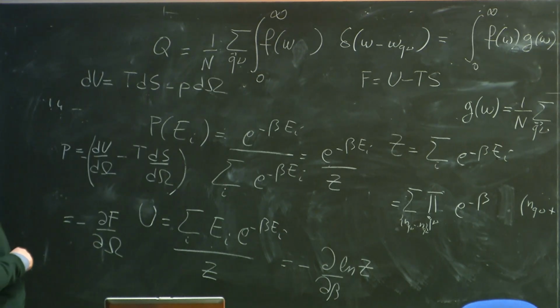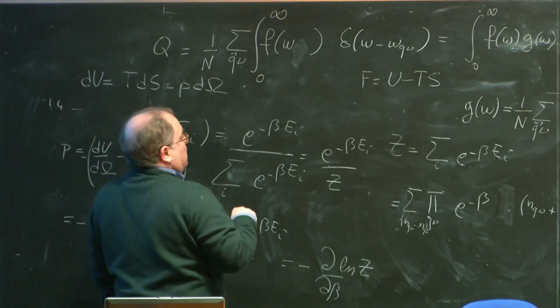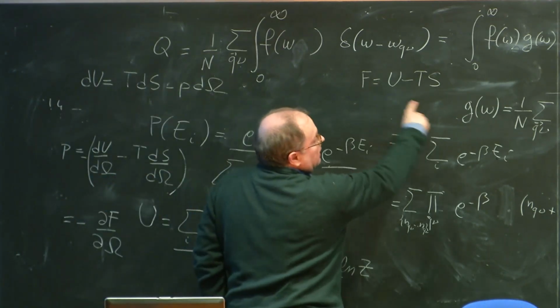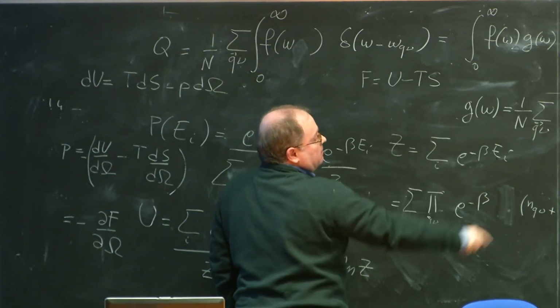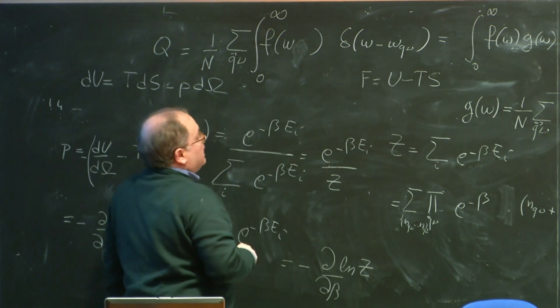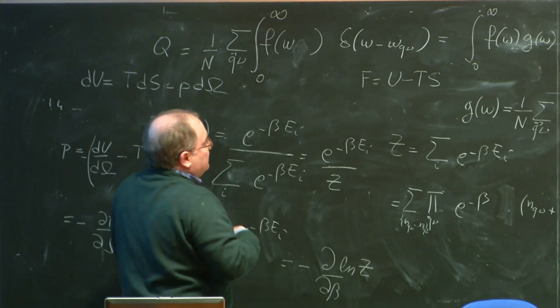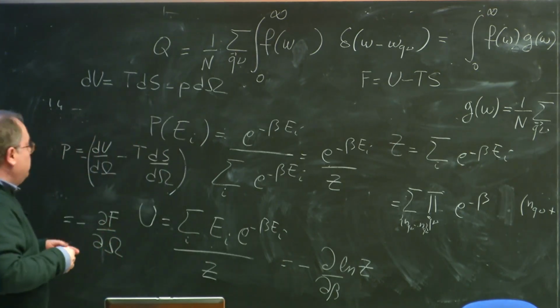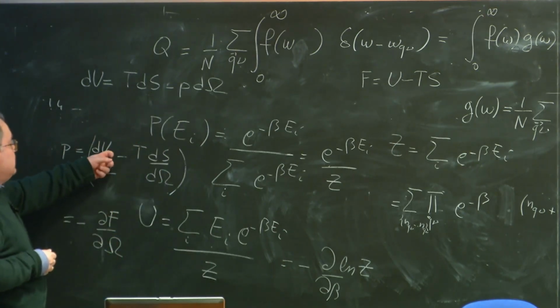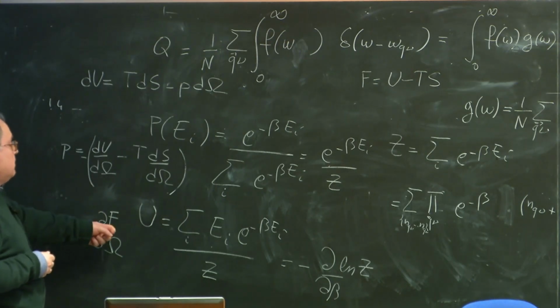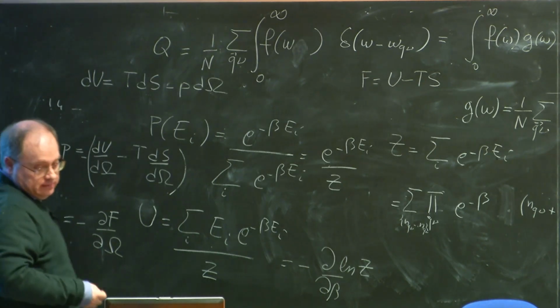The minimum of the free energy with respect to the volume will give us the equilibrium volume of our solid. And so the idea of the quasi-harmonic approximation is that we calculate the free energy. We have seen how to calculate the free energy from the phonon frequencies. We calculate the free energy for several volumes. And so exactly as at T equals 0, we minimize the energy with respect to the volume. At finite temperature, we minimize the free energy at that temperature with respect to the volume.